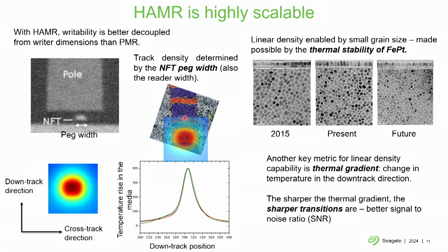HAMR also allows us to have higher linear density because the downtrack resolution is now determined by this measure that we call thermal gradient. So this is the temperature rise in the media as a function of the downtrack direction. So this measure is called the thermal gradient. So the temperature drops off very quickly, so that means we can write very sharp transitions. Add to that we can use smaller grains, which enables us to write sharper transitions. We've actually demonstrated, Seagate's actually demonstrated 5 nanometer grain size media. It's not something we can put in a drive today because it's experimental, may not be completely reliable yet, but it has been demonstrated and the media teams are working on that.